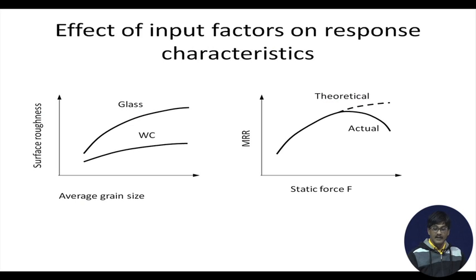this is not dealing with MRR, this is dealing with surface roughness. Now, this becomes important. Why should surface roughness in case of glass be higher compared to surface roughness obtained for material of tungsten carbide? This is because the craters or the hemispherical chunks which are removed, these are small in case of tungsten carbide due to high workpiece hardness. So, it forms smaller craters, this forms larger craters, and therefore, the cumulative effect of having such craters on the surface gives rise to higher surface roughness for glass and lower surface roughness for tungsten carbide. Okay. So, main reason is smaller craters, larger craters, craters being formed by the hemispherical chunk removal.